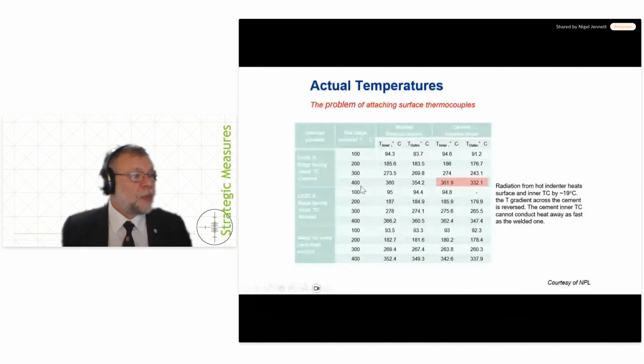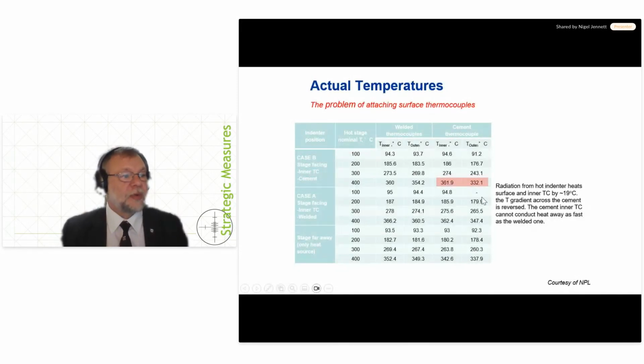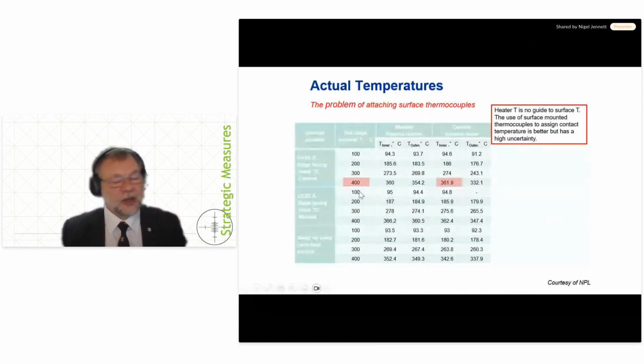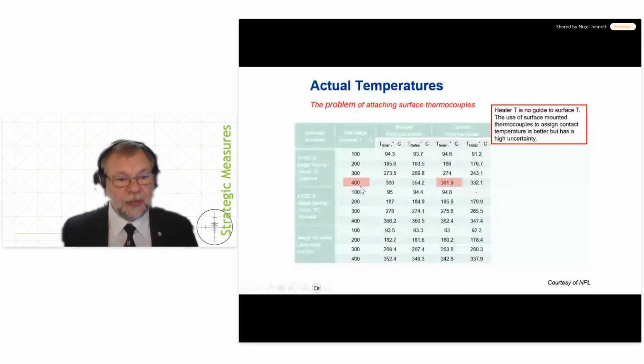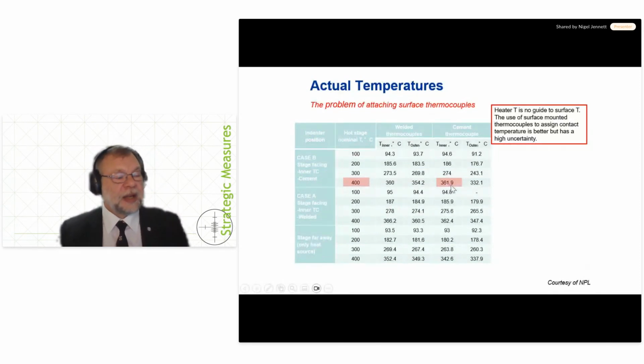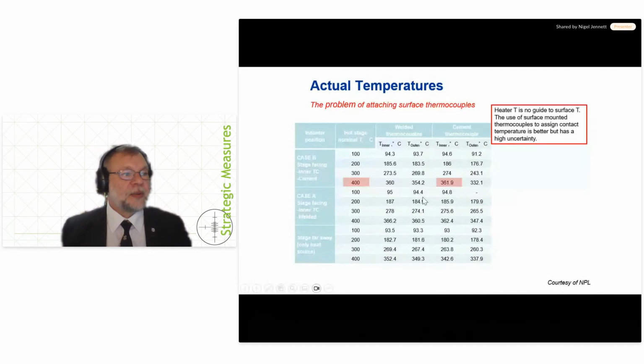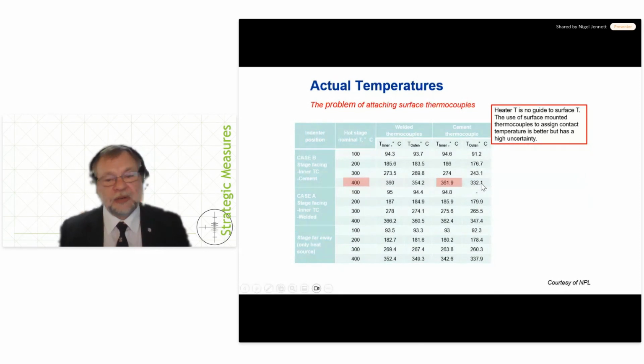And if you put radiation from the indenter in front of the sample, then you get an increase in temperature above what you measure when the cup is away, as we talked before. And we have some very weird readings, which I don't understand at all, about the outer one happening there. But what you can say for certainty is you can't take the hot stage control temperature. If you want to take the inner temperature, well, that's a better indication. But of course, you can't stick a thermocouple where you want to indent. So you're likely to be forced to use an edge thermocouple, in which case you could be 20 or 30 degrees out from where you think your temperature is. And that may or may not be a problem.